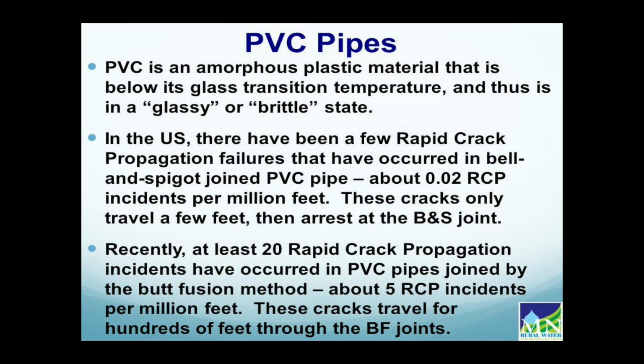So it's in a glassy or brittle state. In the U.S., there have been a few RCP failures that have occurred in bell and spigot joints. When these failures occur, the crack generally travels as far as the bell and spigot joint, and then it stops. There's a discontinuity between the bell and the spigot, and that discontinuity stops or arrests the crack. Failure rate is about 0.02 failures per million feet, and they only travel a few feet and then arrest at the joint.